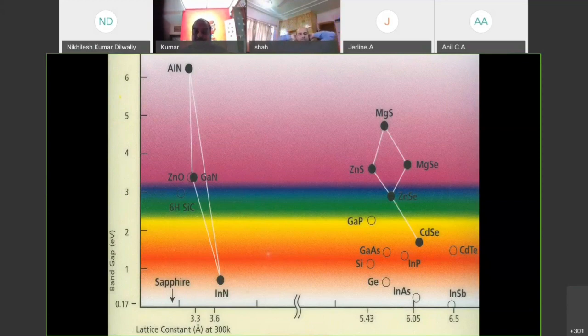So the light emission can be in the visible region, as you can see, from something like red to blue, or it can also be in the ultraviolet. What is the purpose of this? As you know, the white LED is nothing but a mixture of RGB, that is red, green, and blue. If you mix the red, blue, and green appropriately, put a Fresnel lens, or just have a phosphor and make it shine on this, you will get the corresponding white light. Or you can take an ultraviolet LED and make it fall on a yellow phosphor, and that yellow phosphor will release white light. So this is how it is used.